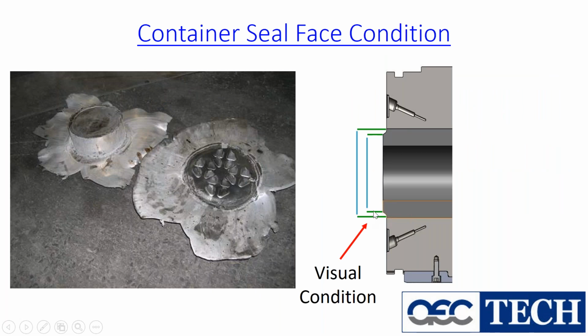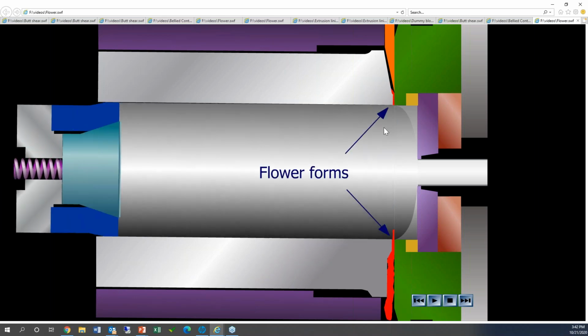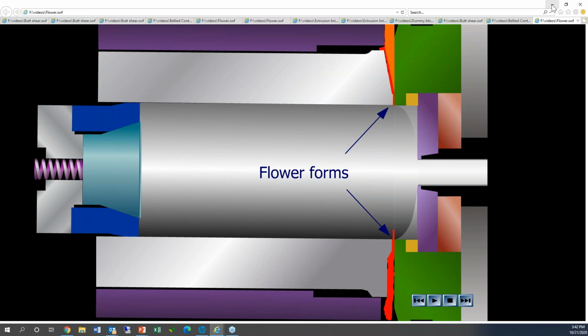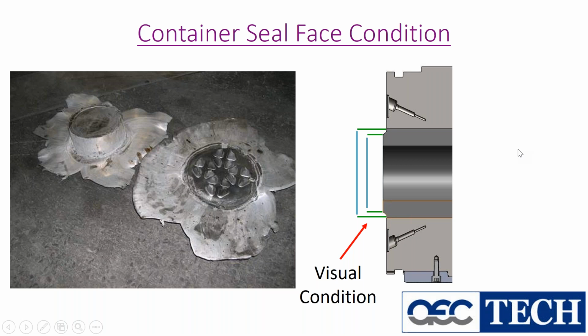We start to see flaring. So any of this visual damage that you see, again, if we start getting chipping away on those faces of the container, we're going to start to see buildup of aluminum on the face, which is going to, hold on, boom. See that container tilt? As soon as you get that container tilt, what happens? Right away, we've reduced that clearance between the OD of the stem and the ID of the container. Maybe on a 30-inch container, that's not a problem. Maybe on a 50-inch container, that's a problem. But either way, it's axial load on the stem and the block. Now I'll continue this. Watch as we go to extrude, look at all the aluminum coming out, and then we get our flowers. And don't get me wrong, I love seeing some of these things that are anodized and hanging in a plant, in a factory. They look really cool, but it's probably one of the biggest oops moments that can happen in extrusion.